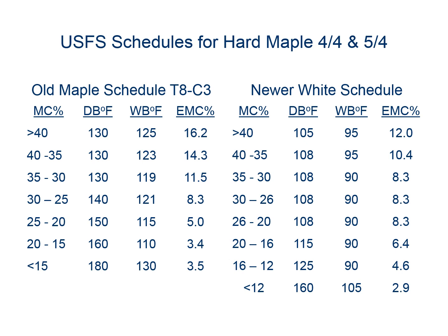But if you notice, we really don't crank the temperature up a lot until we get down to that 20%. That's kind of a magic number. We can go hotter there. So if you look at the right side, 20 to 16, 115 degrees, 16% to 12%, we go 125, and less than 12, we go to 160. So as the wood gets stronger, we can accept more stresses from the drying in the kiln.